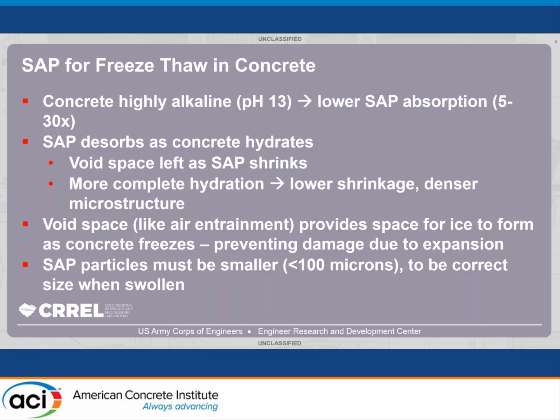And so as the SAP desorbs, as the concrete pulls water and internally cures, the void space is left from the SAP. So as the water goes into the concrete, you leave those voids, and that's kind of what air entrainment does as well, is it leaves those pores for water to come in and have room to expand.